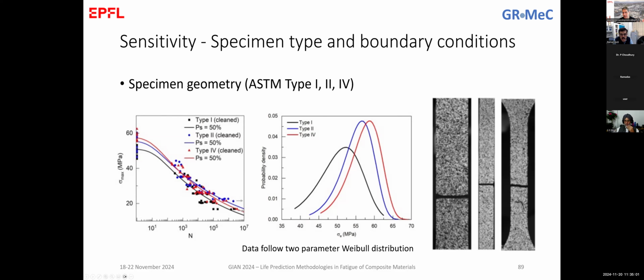And here is the big question. ASTM says, whatever specimen you take, if you have a good failure at the middle, as we have here, you should have the same results. And what we've seen is that we don't have the same results at all. And if we compare even the average values, the type 1 gives around 52 megapascal as the best probability at failure, and type 4 specimen goes to 62. So this is more than 20% different properties estimated only by changing the specimen type.